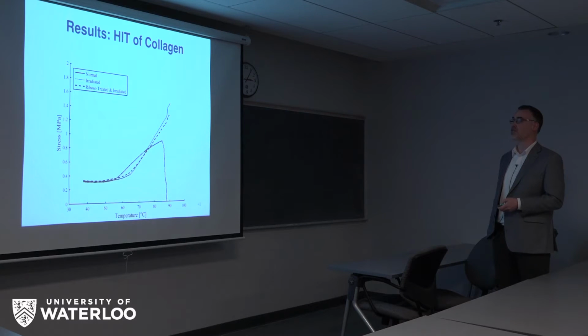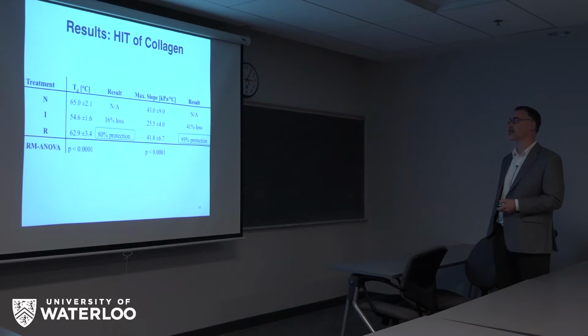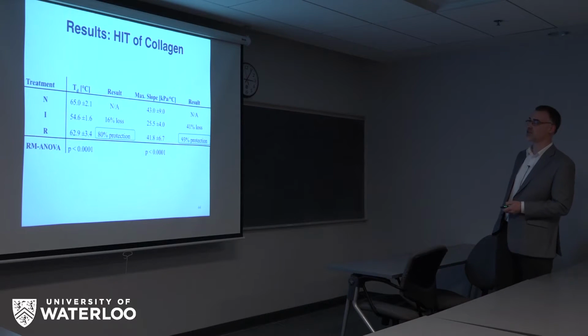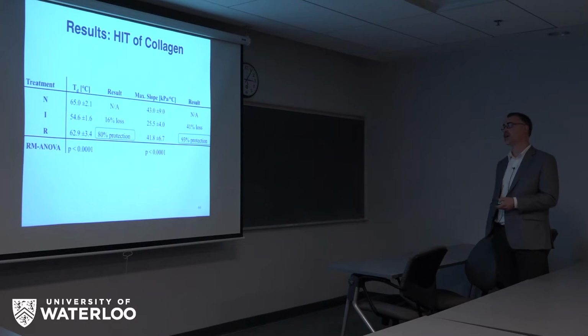Then just to confirm the effects in the collagen again, these are the HIT curves. Normal and ribose-treated are almost the same. And there's your irradiated group failing early, with 80% protection of the melting temperature and 93% protection of the connectivity measurement.